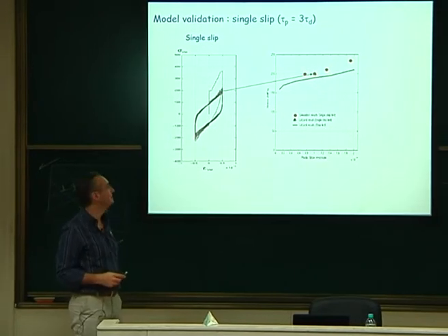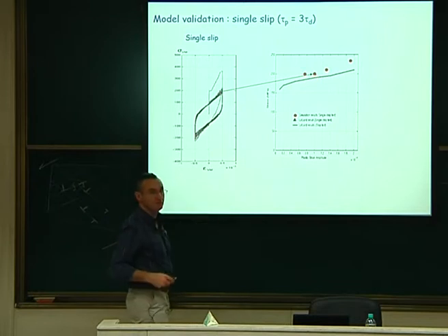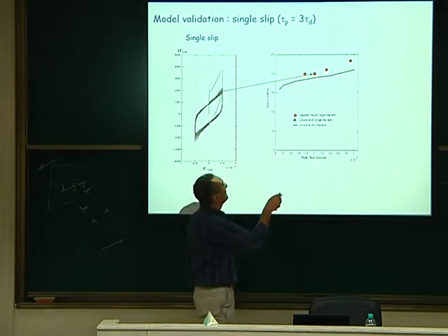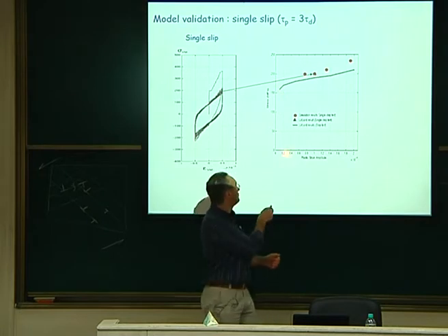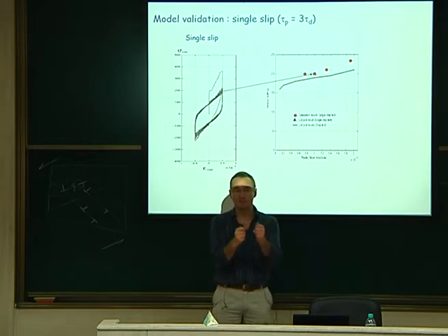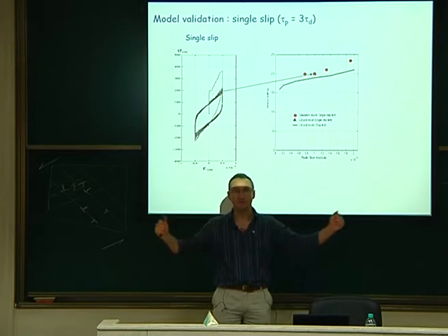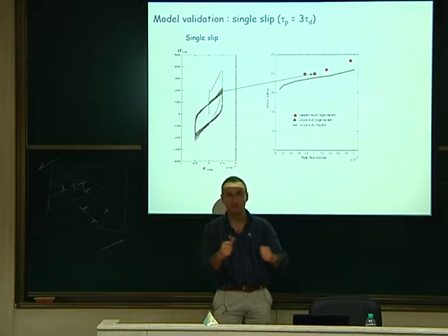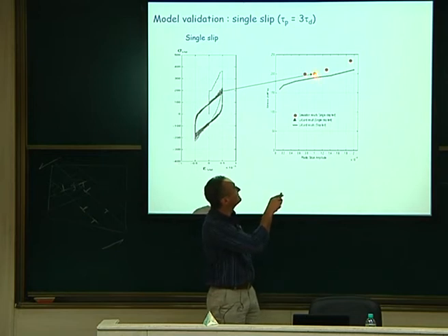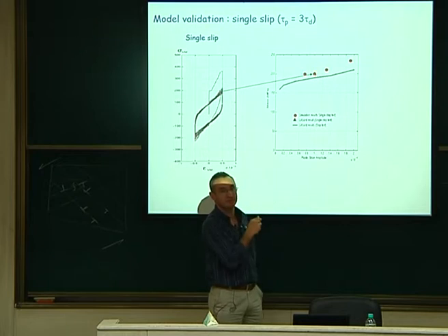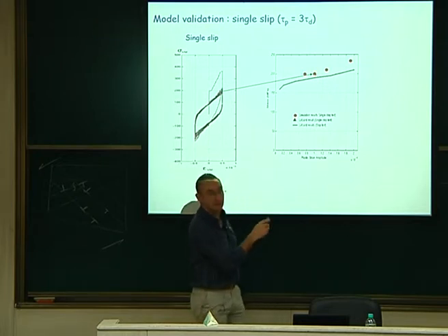You can see how they are located in that curve. The continuous curve here, just for your information, was done by Lee and Laird also. At the beginning, they imposed a given plastic strain, and then this plastic strain amplitude was continuously increasing with the deformation. So it's a continuous increase of your plastic strain, and you can see that the stress in that case is a bit lower than if you impose that directly from the beginning. Am I clear like that?